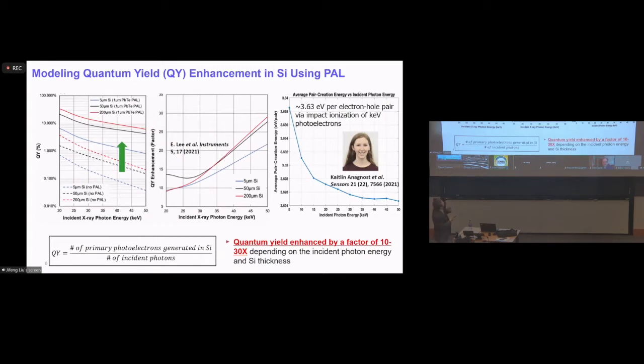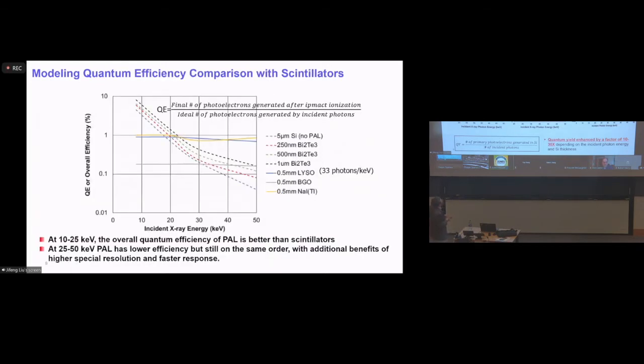So basically, there's a semi-empirical equation saying that it takes about 3 times the band gap energy to produce one electron by impact ionization. And Professor Fossum's student, Caitlin, analyzed this in a more systematic and rigorous way and proved this is true, although there's some energy dependence, the variation is very small. So roughly it takes about 3.6 electron volts by impact ionization to generate another electron-hole pair in silicon.